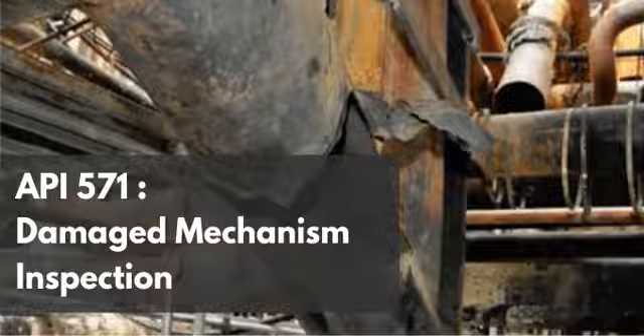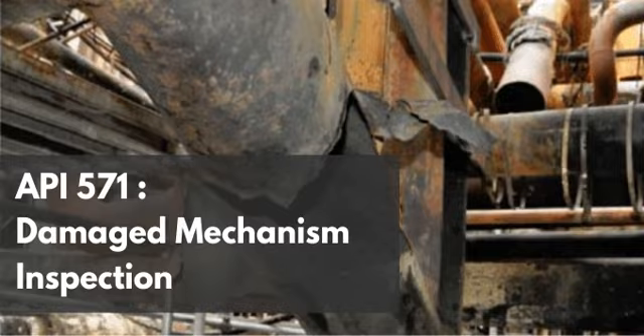I want you to really visualize the inside of a fired heater tube in one of these units. It is not just some warm liquid gently flowing through a household plumbing pipe. It is a high-pressure, ultra-hot, violent, roaring environment. And the data highlights a very specific, localized risk within these turbulent tubes. It states that the coke deposits themselves act as a direct physical source of carbon that promotes localized carburization. We touched on this during the decoke cycle discussion, but let's expand on it a bit. The coke is not just a thermal insulator. It's an active chemical antagonist.